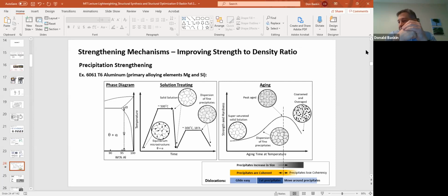But in the real world, where you have to make aluminum quickly in order to make money, you don't have time to do that. So there's a step called artificial aging, where you reheat the material to a lower temperature than you did for the solution treatment, and you precipitate out these little precipitates in a much quicker fashion. So maybe only a couple of hours rather than days.